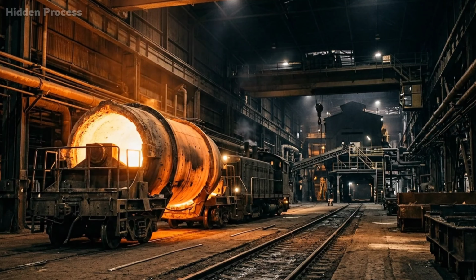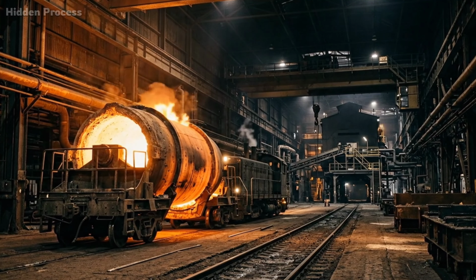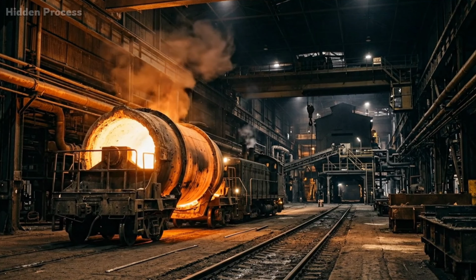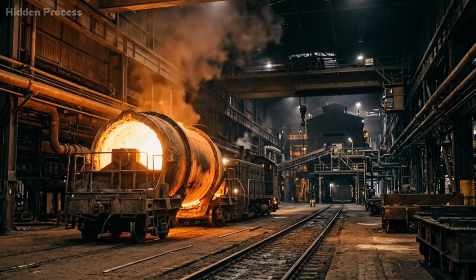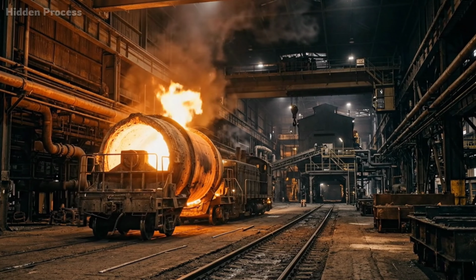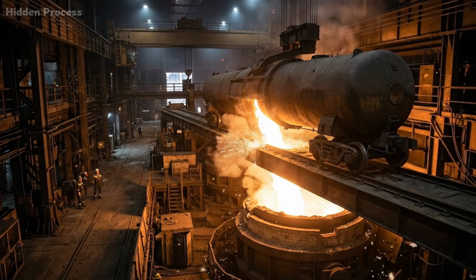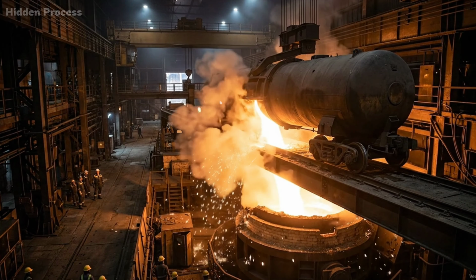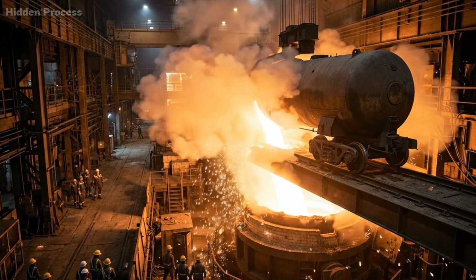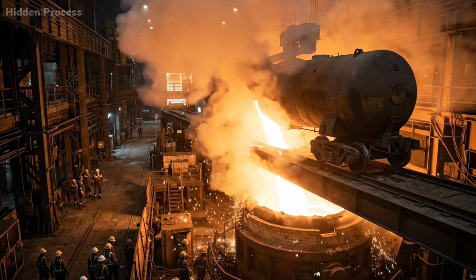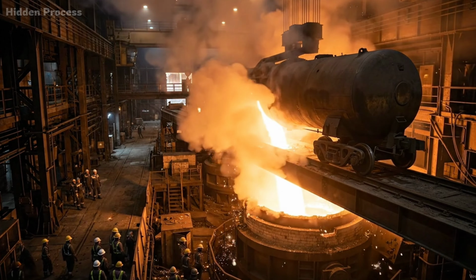The torpedo ladle of liquid pig iron is transported, still at 2,500 degrees F, to the next stage, the basic oxygen furnace, or BOF. The ladle tilts, and the molten pig iron, all 300 tons of it, pours into a giant vessel shaped like a massive barrel, lined with more refractory brick.